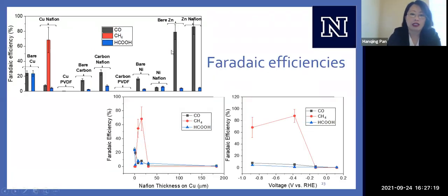Couple of the experiments that we did here. First thing we did is switch up our substrate. We want to know, does the metal underneath even make a difference? So we changed it up. We tried copper, we tried nickel, we tried carbon paper. And product is changing. Faradaic efficiencies here is changing. So the metal that's underneath absolutely makes a difference.